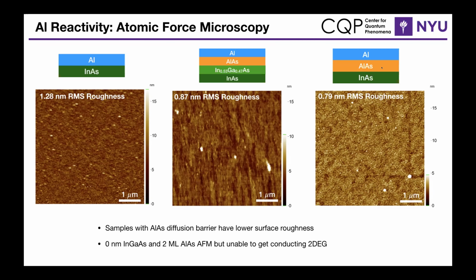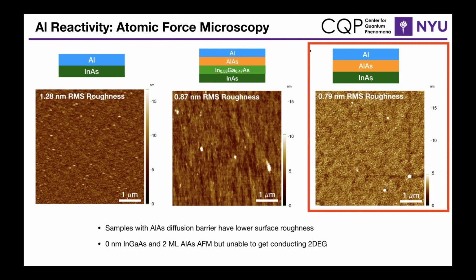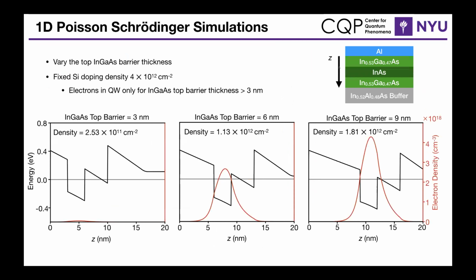But a problem with this is that you actually can't get a conducting 2DEG, or this sample was not conducting, and this is a problem when you want to make gatemon qubits on it. And to study this, we actually went back and tried to simulate the charge density and conduction band energies. And we found that you actually have to have a thicker InGaAs top barrier in order to get the conduction band to dip below the Fermi level and start occupying electrons into the conduction band.